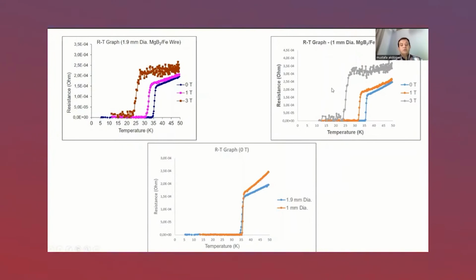Actually, the difference between them is the bottom broadening of the TC offset behaviors of the wires. So you are seeing broadening on the 1.9 millimeter diameter's offset value. This was expected actually, because we were thinking 1 minute may not be enough for the reaction of the MgB2. So you are seeing the differences between the diameters at the bottom. So 1 millimeter diameter transition is better than a 1.9 millimeter diameter.